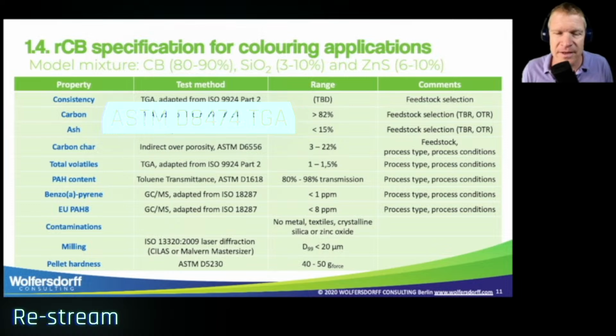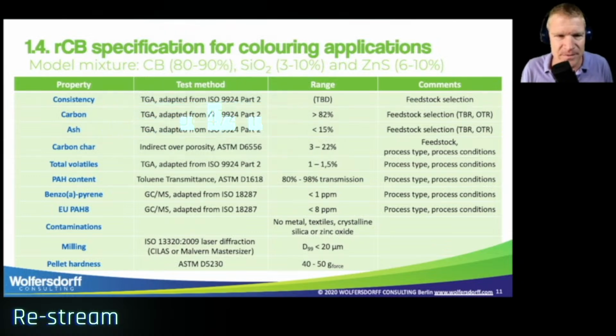Now, the carbon comes from the TGA, the ash comes from the TGA. I would recommend having more than 82% carbon for a coloring recovered carbon black, which means the ash content should be less than 15%. Of course, if you can have a recovered carbon black that has no ash content, that would be even better. Carbon char might be between 3 and 22%. We'll get back to the carbon char in one of the next slides. This is depending on the feedstock, on the process type, but also on the process conditions.